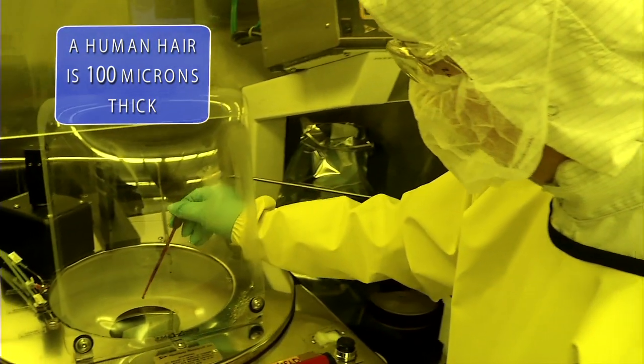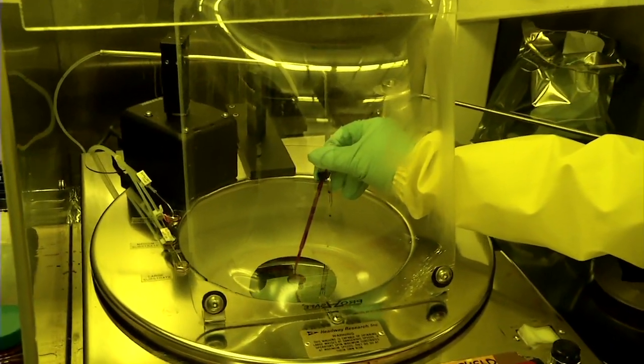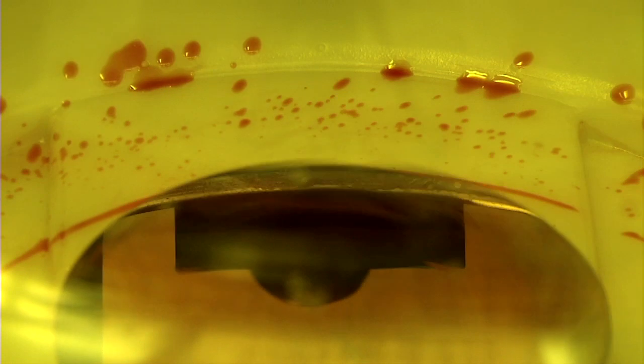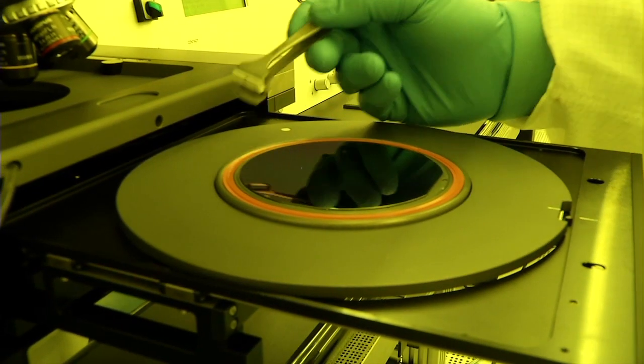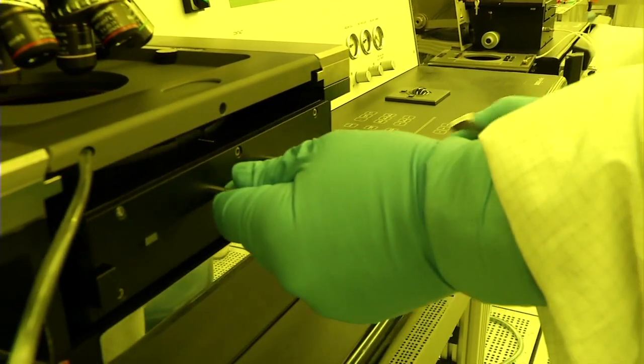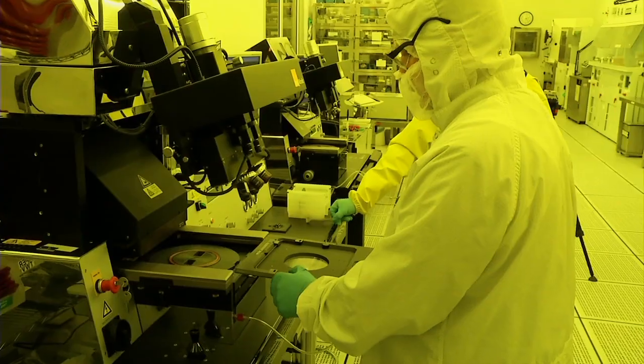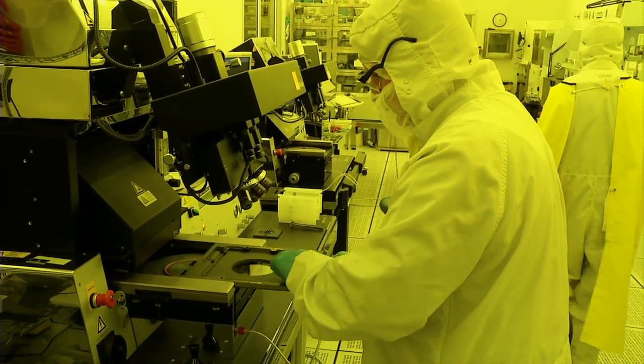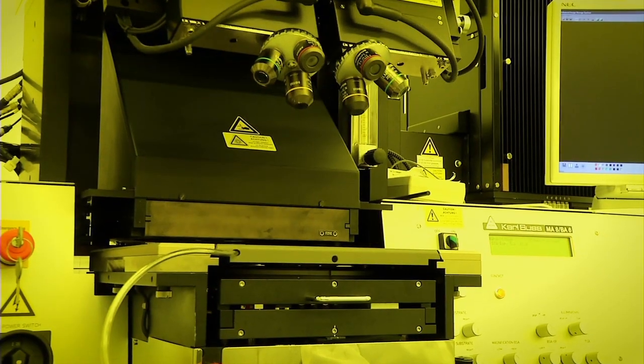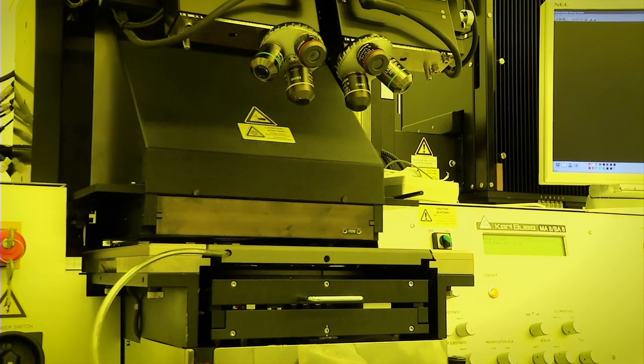The first step in lithography is to apply photoresist to the substrate. This is done by spinning on a liquid suspension of the polymer in the spin coater. The coated wafer is taken to the photomask aligner, where the chrome-on-quartz mask that was created by the design and layout is placed in extremely close proximity to the substrate and aligned to existing patterns within a micron of accuracy.